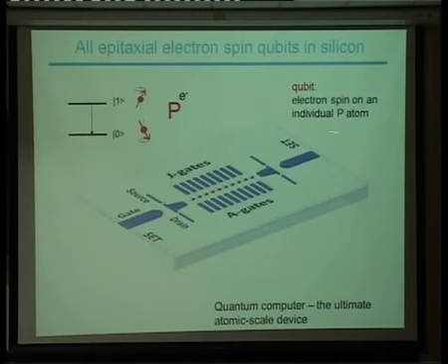The critical part of this device is it's all epitaxial, so we have no interfaces or surfaces nearby. Once we put these atoms on the surface, we encapsulate with silicon by MBE, and we take those donor states away from the surfaces. So we get this nice, pure donor-like potential that we're going to use.